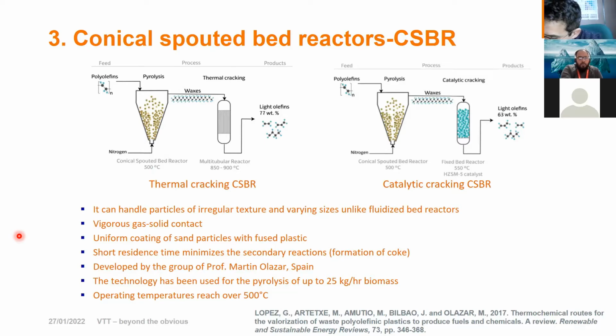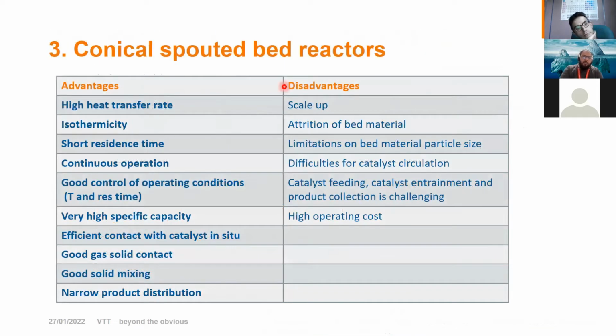Short residence time will minimize the secondary reactions, which means the formation of coke is minimized. This technique has been used in the pyrolysis of biomass up to 25 kilograms per hour, and operating temperatures can even go up to 500 Celsius. It can be used both in thermal and catalytic cracking. If I look at the advantages and disadvantages of this type of system,